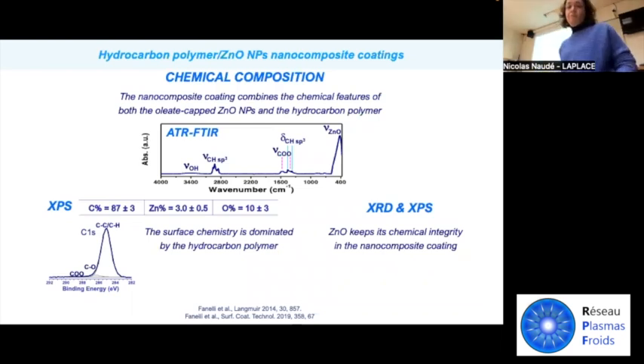Let me show an overview of the typical chemical and morphological properties of the coating that we were able to deposit by using this approach. Here you can see, first of all, the classical ATR-FTIR spectrum of the coating, which shows clearly that the coating combines the typical chemical features of both oleic-capped zinc oxide nanoparticles, in this case, and the hydrocarbon polymer formed through the plasma polymerization of the organic solvent.